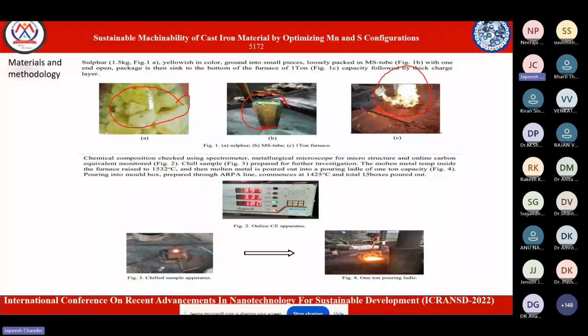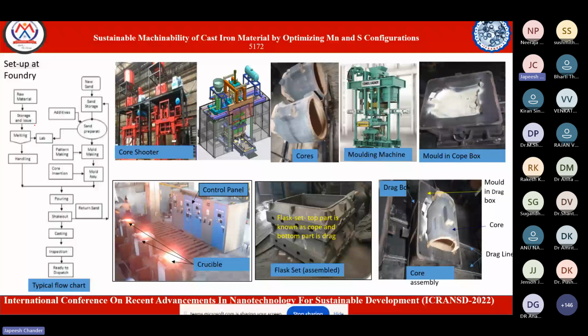There are other ways of putting sulfur, because iron sulfide is available, and different alloys are available which we can take and put. So this was a research on how we can increase sulfur if we use pure sulfur, along with manganese. This was the complete process: raw material, storage, melting. We send the material to the heat lab. We understand that okay, the composition is correct, FG260: carbon, manganese, sulfur, phosphorus, all in proportion in the range as specified. And then we pour the material.